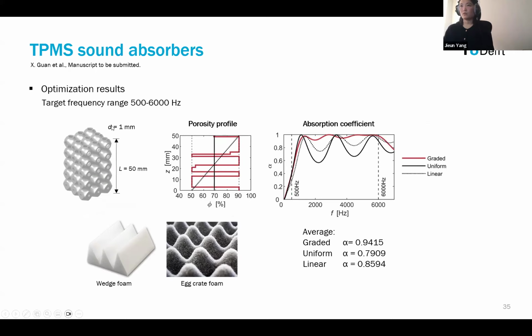So we used unit cell size 1 millimeter, and the total thickness of the sound absorbing layer is 50 millimeters. You see only these 5 unit cells in this figure, but this is not really the actual geometry. So we have 50 unit cells along the thickness of this porous layer. So the optimal porosity profile is this red curve. You see that the optimal profile is actually jumping from high value to low value quite a lot.